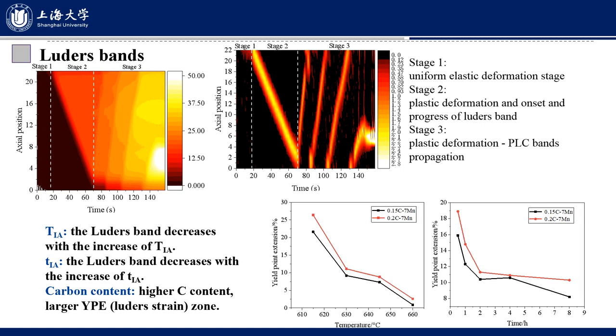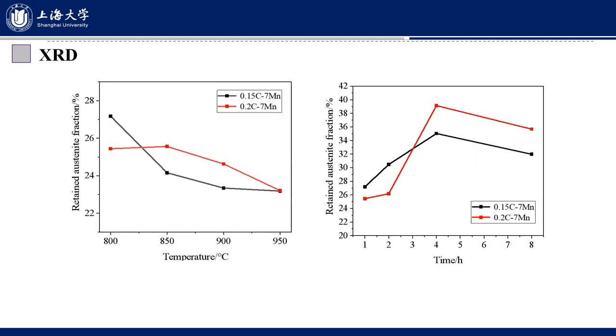It is clear that the Lüders band decreases with the increase of intercritical annealing temperature, and the Lüders band decreases with the increase of intercritical annealing time, and the carbon content shows an influence on the yield point elongation behavior of the steel. This slide shows the XRD result of the steel.